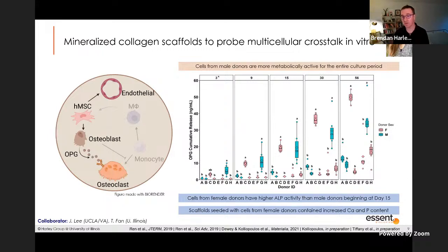And we used a single one of our material variants to ask the very important question. If we have a single biomaterial that we know is really good for bone repair, do we see differences in how different patient cells behave on that? And so Aliki and Alec have screened a wide number of different factors associated with bone repair and found some really interesting observations, at least here linked to donor sex, where we find that cells from male donors were much more metabolically active in our scaffolds, meaning they were proliferating and growing faster compared to female donors, which might sound like male donors would be better. But one of the other things that was really interesting, that wasn't always the case.